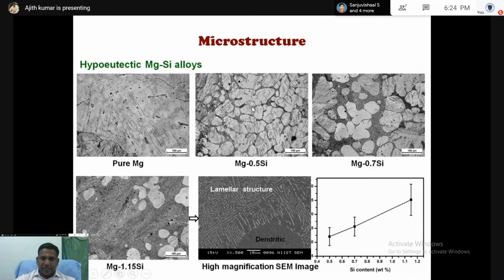You see, the white region is the alpha Mg. Initially we can see two regions only, one is the white region and one is the gray region. The white region is changing with respect to silicon. That white region looks like a dendritic kind of structure. With increasing addition of silicon, the dendritic structure is reducing. At the same time, in the interdendritic region, some gray phases are coming. In 1.15 silicon, the gray region is more.